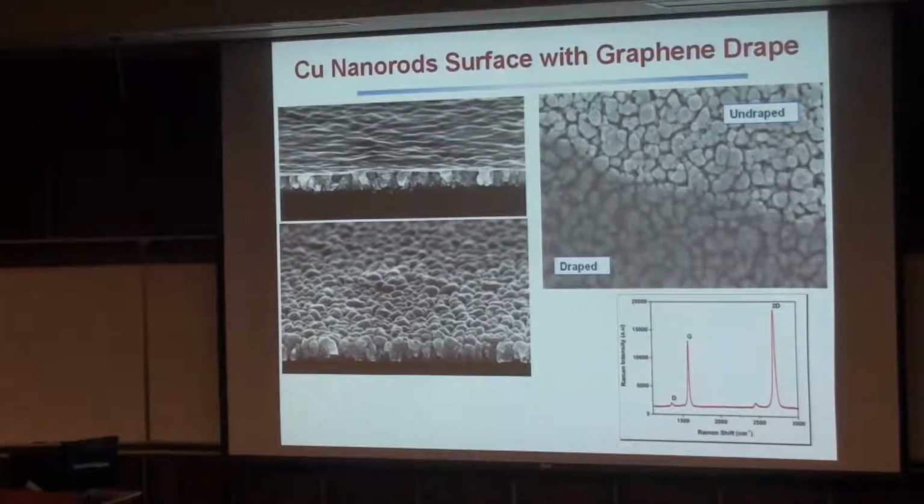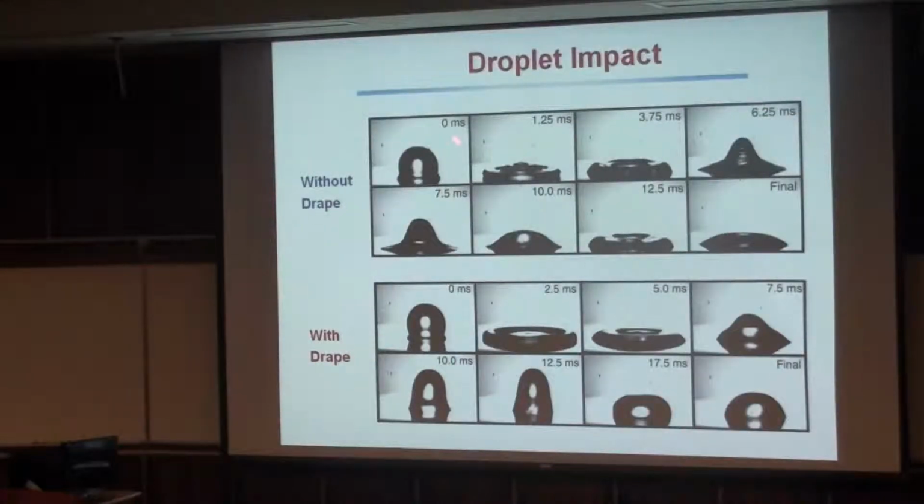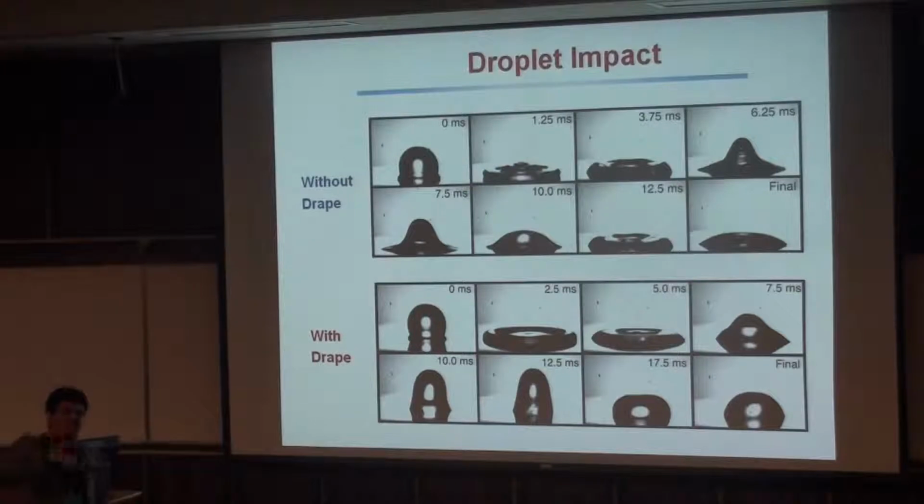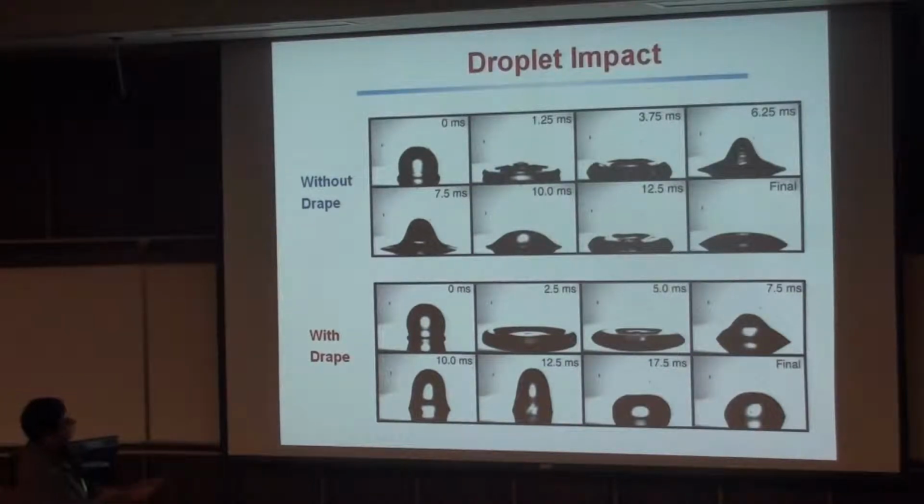But when you do impact of water droplets on this, so for example, I take a surface like this and I impact it with a water drop, because the drop hits the surface with some energy, it forces itself into the surface, it displaces these air pockets. And you go from the Cassie state where the drop is floating on the top, you go into the so-called Wenzel state. Right? And when that happens, the drop hits, it spreads, and it actually penetrates into the surface, displaces out all the air pockets, and then it gets stuck.